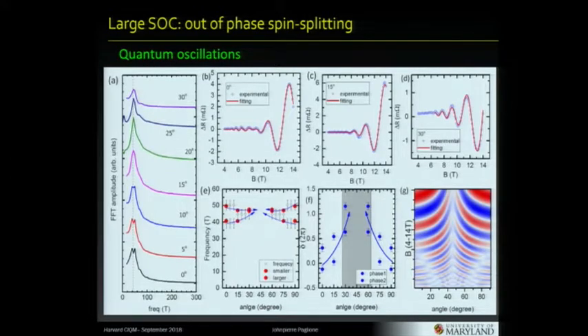And so I can show you, here's some data fit to some function that actually has two frequencies. So you remember there's two spin split Fermi surfaces. There's one here and one here, and they're almost identical, so you get some beating effect, and you can actually see that here. You see this is growing and then it dies, right? It gets smaller and then grows again. And you can fit this for different angles as you tilt the magnetic field. So you can see, first of all, that the splitting actually goes away, and then at some point beyond 30 degrees, it disappears. The amplitude goes down.